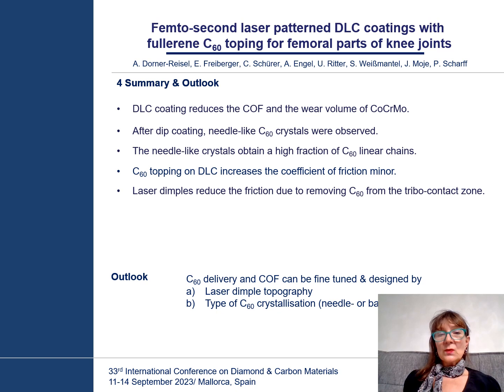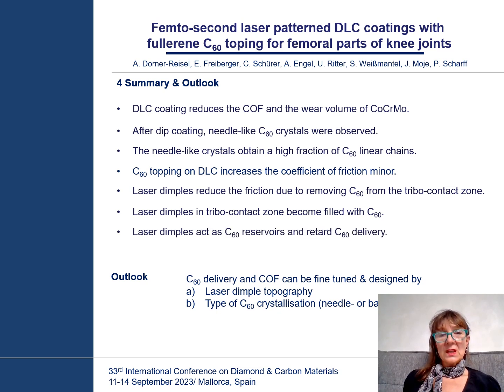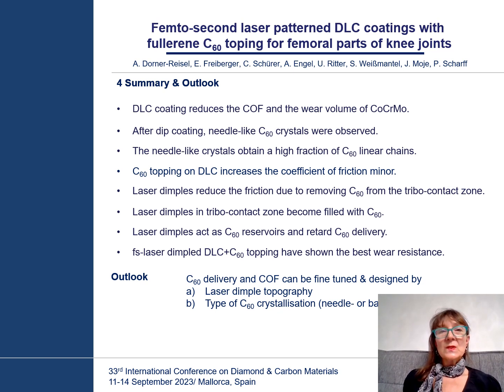Laser dimples reduce the friction by removing C60 from the tribo contact zone. Laser dimples in the tribo contact zone become filled with C60 and act as reservoirs and retard C60 delivery. Finally, femtosecond laser dimpled DLCs with C60 topping have shown the best wear resistance. In future, we would like to investigate different laser dimple patterns, and we would also investigate not only needle-like but also agglomerates of C60 and polygonal crystals.